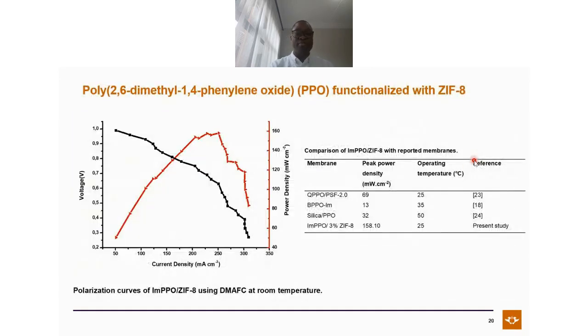We did the performances of the ZIF. As you can see, the ZIF actually had higher output compared to the one which was functionalized with graphene oxide. The graphene oxide had high ion conductivity, but it had about 130 output. This ZIF had lesser ion exchange capacity and was less conductive, but its performance was still high in terms of power output, which is what we want.